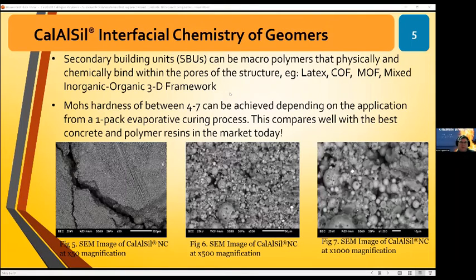If you just get Portland cement, add the correct amount of water, which is usually 66% of the mass of cement that you've got, then you get a Mohs hardness of around about 2 to 3 for Portland cement. The hardness of a concrete comes from the fact that cement crystals grow into the aggregates. That's how concrete becomes very strong and hard. In this situation, CalAlSil resins, we're working backwards, where we've got water that needs to be evaporated, and I've got unreacted particles in the mixture that then react during the evaporation process, thereby leading to significant bonding at the nanoscale and chemical scale.